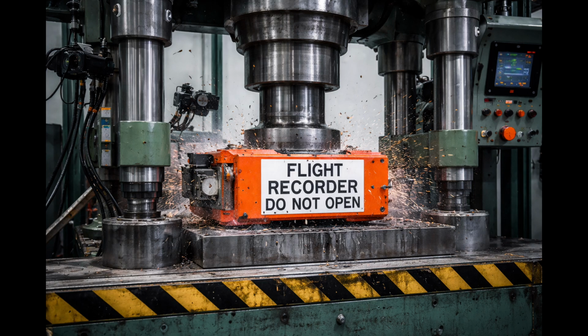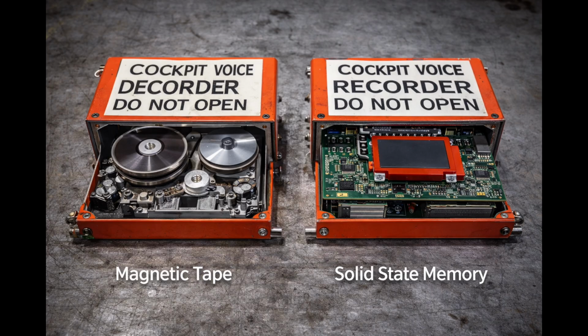Meanwhile, accident investigation itself was evolving. No longer content with surface explanations, investigators adopted forensic methodologies borrowed from metallurgy and fracture mechanics. Fracture surfaces were examined for beach marks, revealing the incremental growth of fatigue cracks. Chemical analysis detected corrosion products that had weakened structures years before failure. Finite element models reconstructed stress fields that had never been measured in flight. The recorder's data provided timing. Physics provided causality.